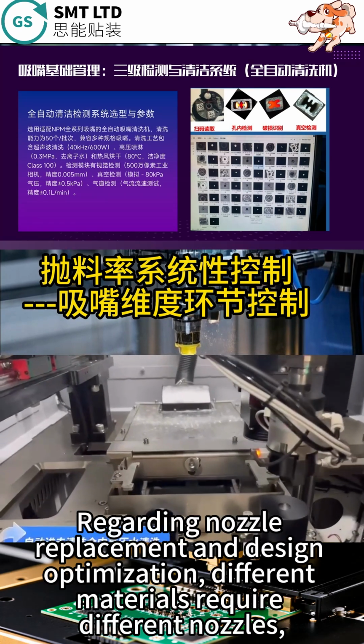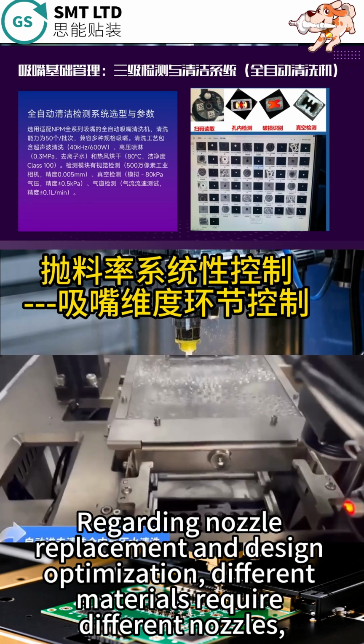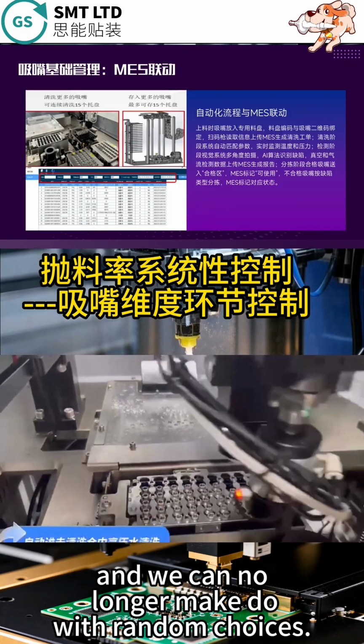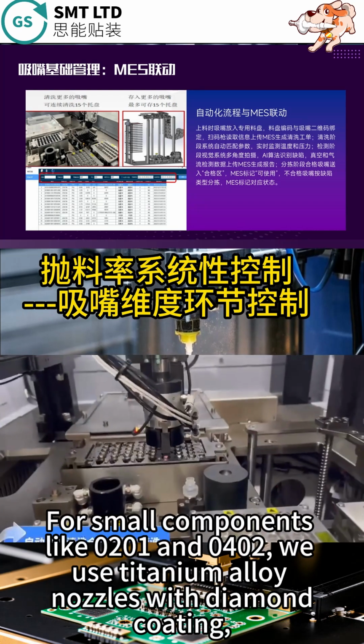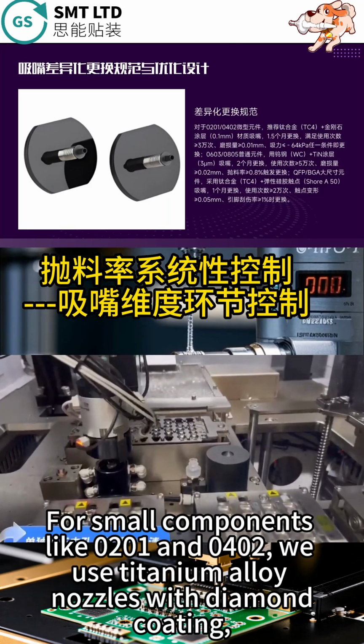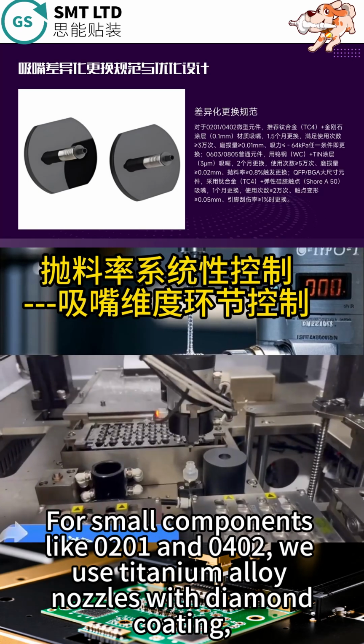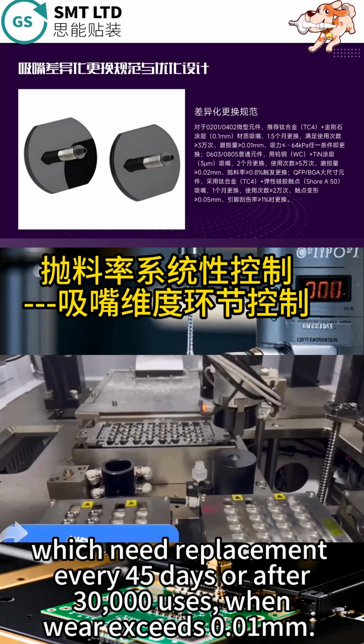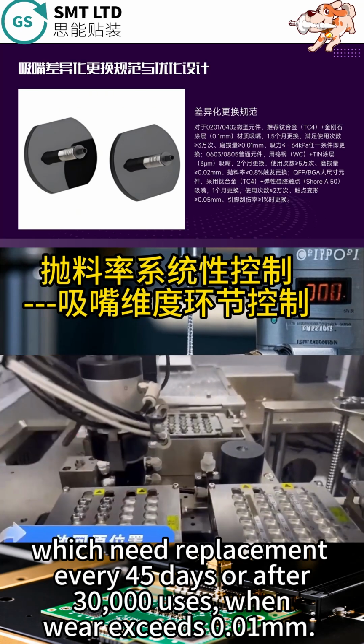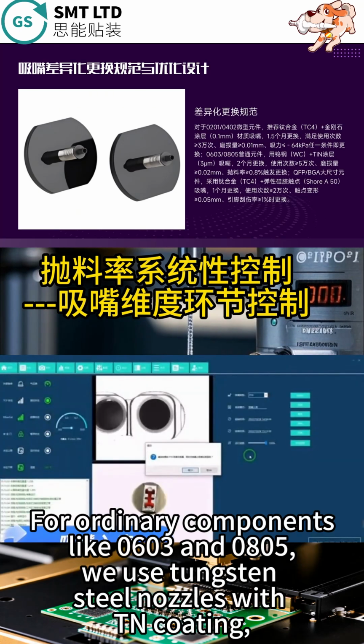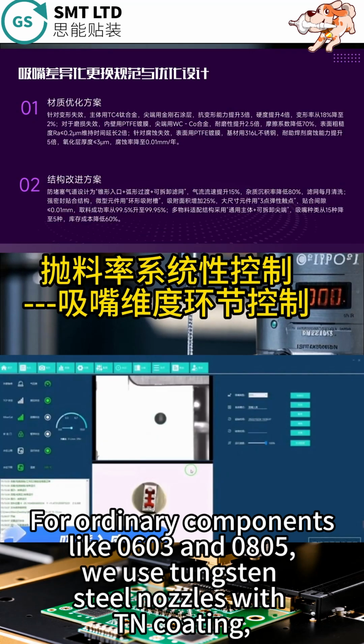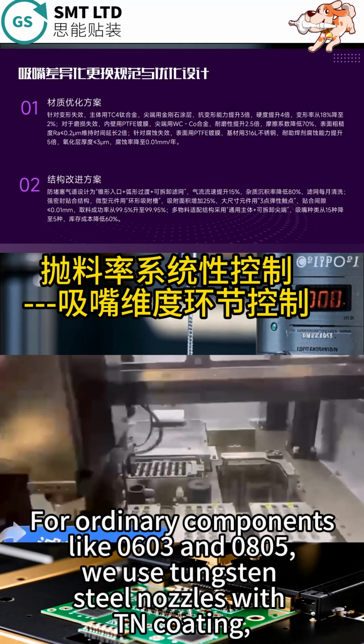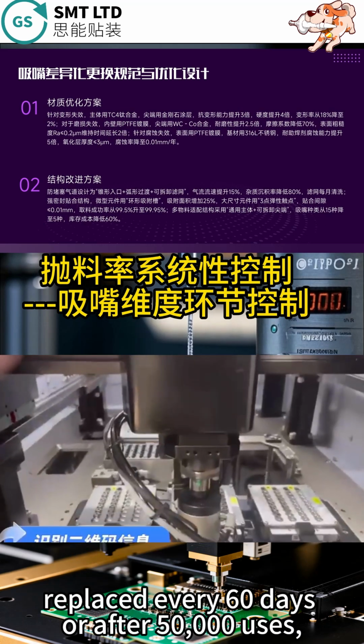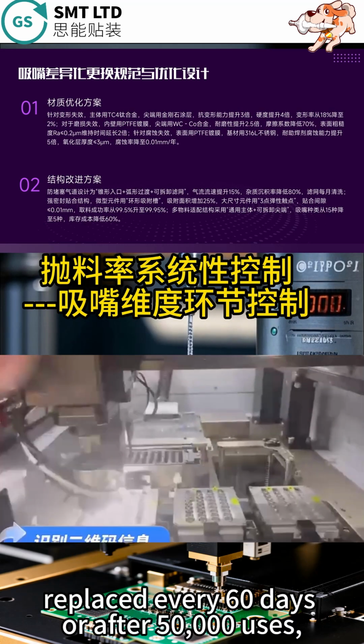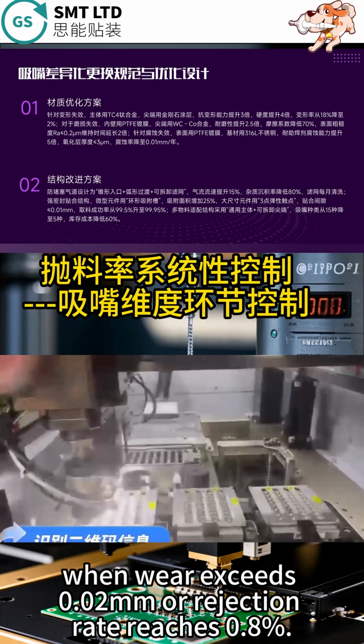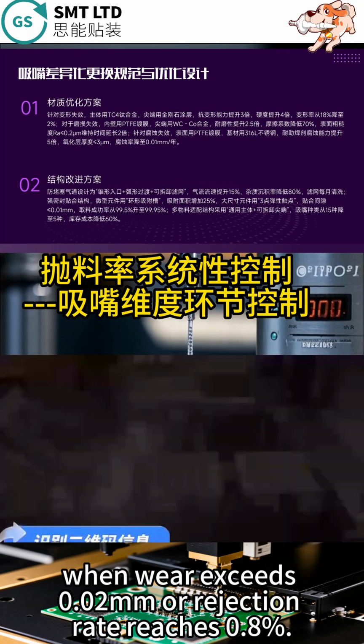Regarding nozzle replacement and design optimization, different materials require different nozzles, and we can no longer make do with random choices. For small components like 0201 and 0402, we use titanium alloy nozzles with diamond coating, which need replacement every 45 days or after 30,000 uses, or when wear exceeds 0.01 mm. For ordinary components like 0603 and 0805, we use tungsten steel nozzles with TiN coating. Replace every 60 days or after 50,000 uses, when wear exceeds 0.02 mm or rejection rate reaches 0.8%.